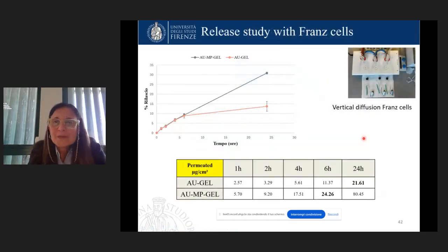We study also the release of usnic acid from the gel. We compare the release of usnic acid from the system micelles in gel and also usnic acid in gel. To study this release, we used Franz cells. We observed that in the case of micelles incorporated in the gel, we have a high release of the usnic acid, different with respect to usnic acid dispersed in gel.